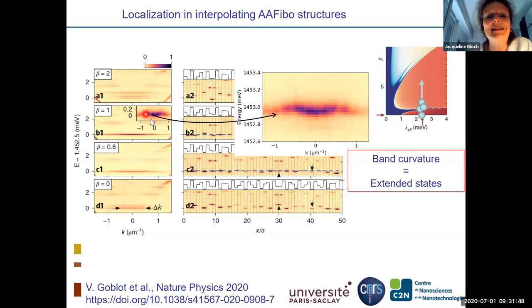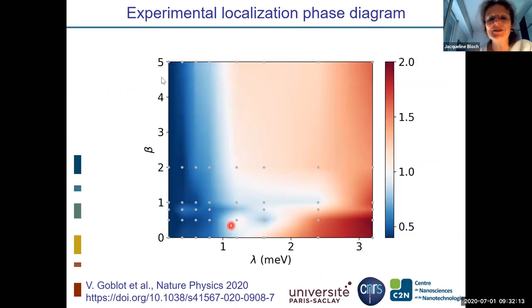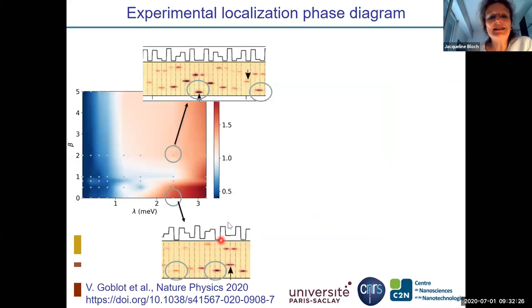What is really interesting is that when you are here and you zoom, you see a band structure appearing in k-space, which means that you have really extended states. This is the demonstration of this first lobe. We go from very localized states to more extended ones for this value, and then again to localized states. By looking at many of these wires, we could retrieve a part of this phase diagram and really see this first lobe of delocalization transition. If we look in more detail, below the lobe of delocalization, the lowest energy states are localized on one letter.